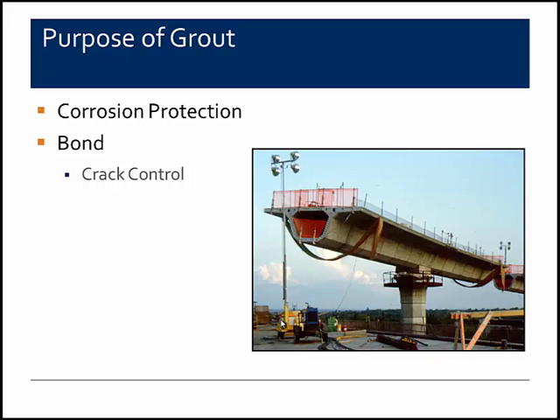In the picture you see here is what's called a balanced cantilevered precast segmental bridge, and each of those concrete segments are actually glued together with an epoxy, and then they're really held together by the post-tensioning tendons. So the bond of those tendons to those precast elements is extremely critical to make sure that you achieve the crack control that's necessary. You do not want to let a post-tension structure crack. That allows chlorides and other moisture and other deleterious elements to get in there and really do some harm to the post-tensioning system.